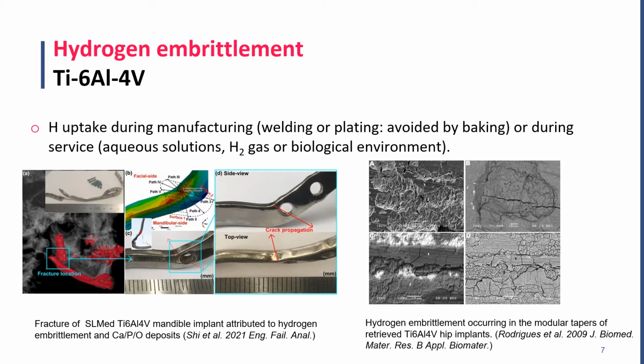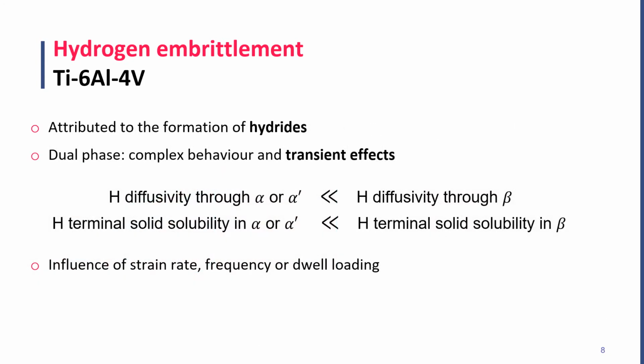As we can see in these two failures, hydrogen embrittlement is also critical in biological environments. Here we see a fracture of a titanium-64 mandible implant attributed to hydrogen embrittlement. And similarly, we see how cracks are nucleating in a hip implant due to hydrogen absorption. This accelerated cracking when hydrogen is present in titanium alloys is attributed to the formation of hydrides, which is a